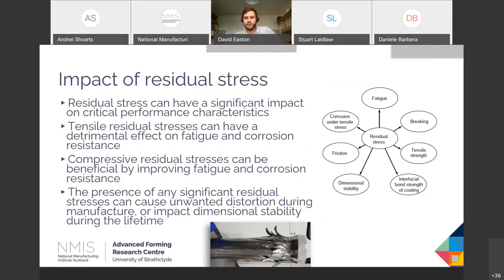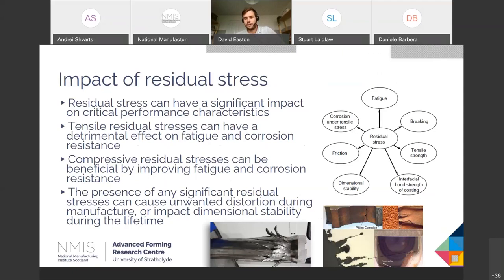And we can see here just some examples of what residual stress can do. Here we've got a flow-formed tube which experienced extremely high residual stresses and enough to actually cause it to fracture. Or we have some corroded material where the corrosion has been exacerbated by the presence of tensile stresses.